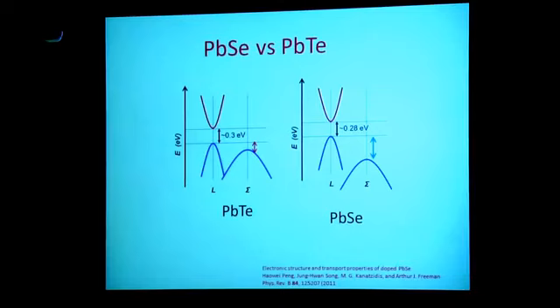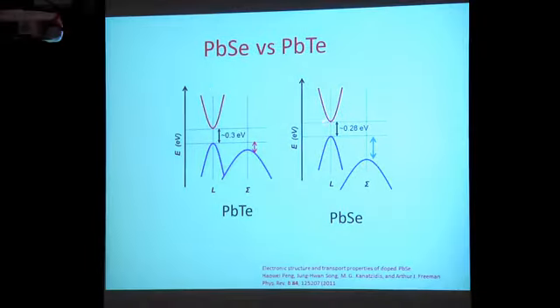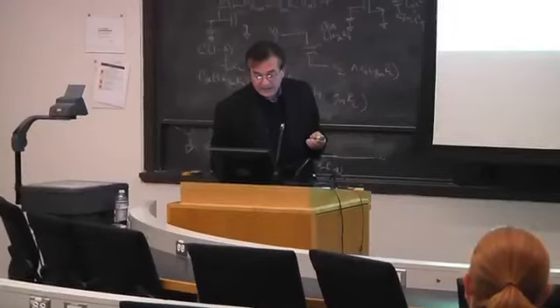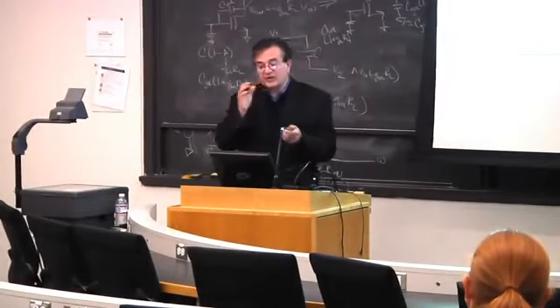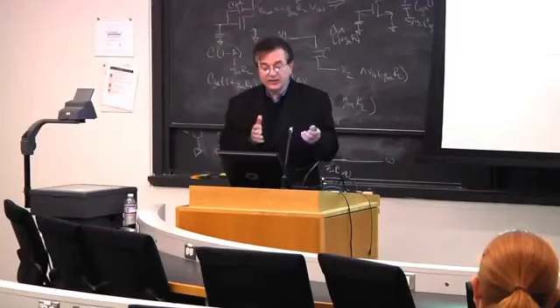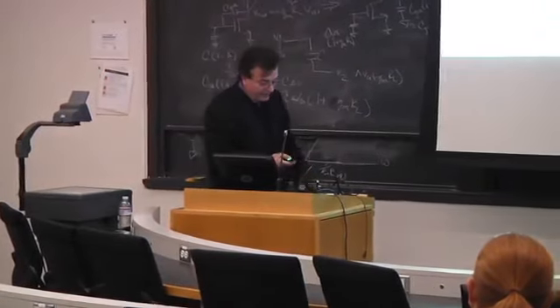Lead selenide is similar but not identical to lead telluride. So here's how they compare electronic structure. I showed you this already. Here's the second band, and this is about 150 millivolts lower than this band. By the time you get to the selenide, it drops. So you may not have this effect, but this stays. This is similar, and that is similar. So we wanted to see how this will behave. So we went to lead selenide, and we wanted to see if we could add lead sulfide to lead selenide, whether we would get phase separation.